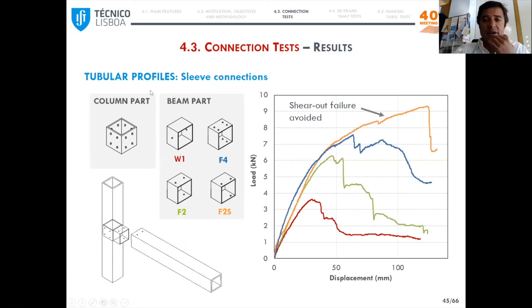So for the tubular profiles with the sleeve connection systems, where we varied the position and also the number of the bolts, you can see here a summary of load displacement curves of the different series. And you can see that for this specific series, where we increased the edge distance, it was possible to avoid shear out failure in the GFRP, which is very brittle, promoting instead bearing failure in the GFRP, which is more ductile, and also the yielding of the steel part. And this led to this nonlinear response.